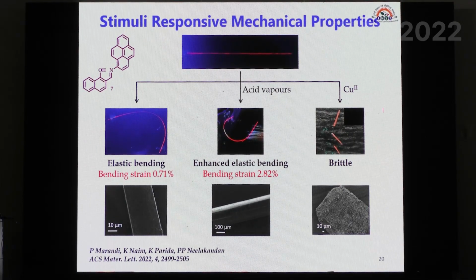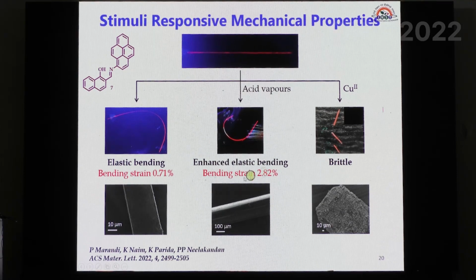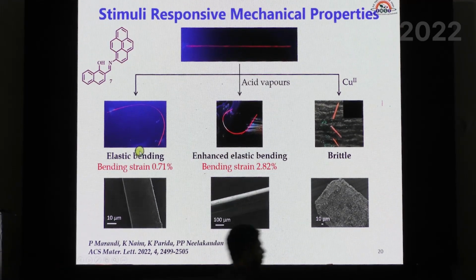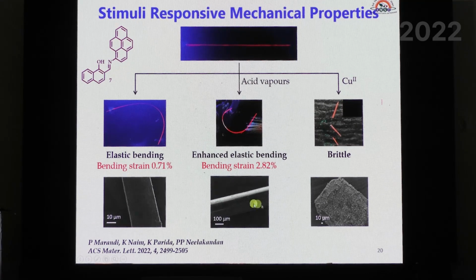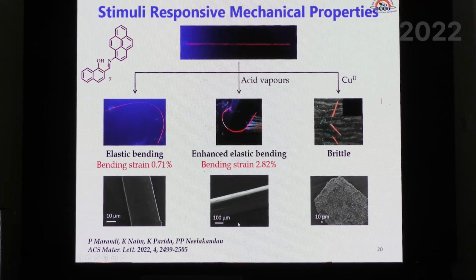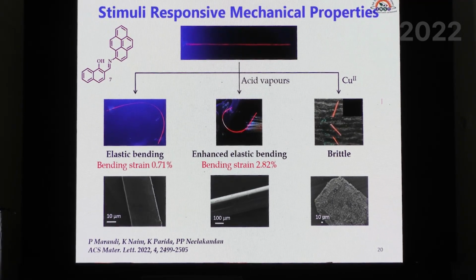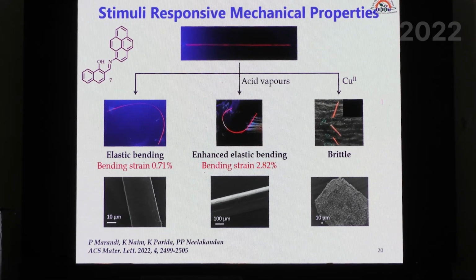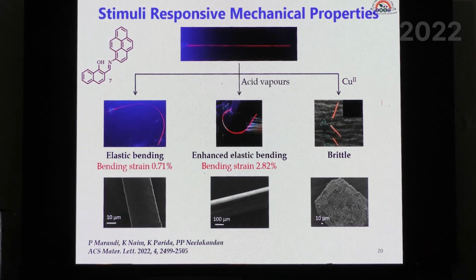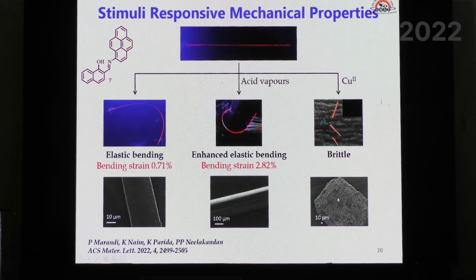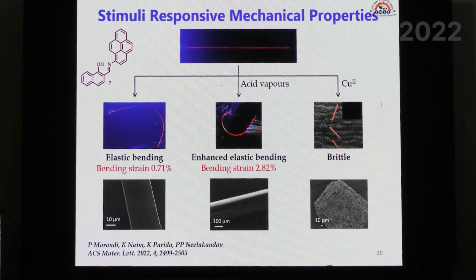We have also looked at the surface of this compound using SEM. You see that in the pristine state or after treating with acid, it has a smooth surface. But when we have treated it with copper, copper is probably deposited on the surface, and as a result, it forms this kind of rough surface. So probably that explains the brittleness of these crystals.